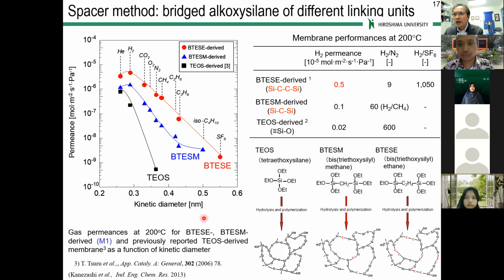So now we fabricate membranes using TEOS, BTESM with methane as a linking unit, and BTESE with ethane as a linking unit. Here we have the permeance plotted as a function of kinetic diameter for TEOS-derived, BTESM methane-derived, and BTESE ethane-derived membranes. When you look at the permeance ratio of hydrogen over nitrogen, TEOS-derived membranes show more than several hundred times difference. Hydrogen is more permeable than nitrogen, okay? But by changing the precursor from TEOS to BTESM and BTESE, you can see increased permeance, more than 1 order of magnitude increase for hydrogen.